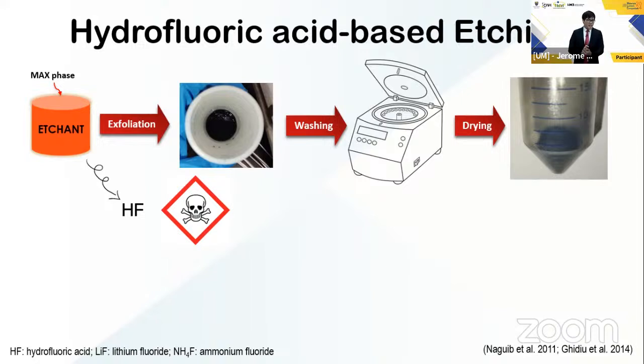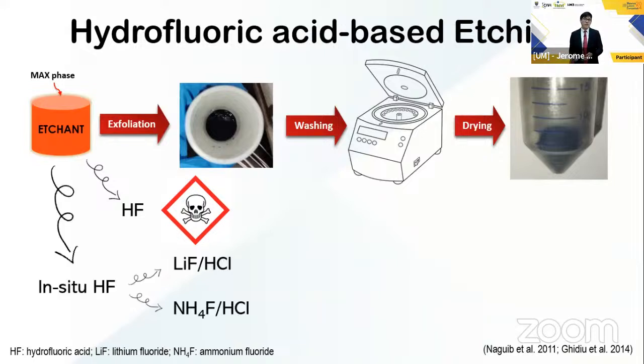But hydrofluoric acid, as all of you know, is one of the nastiest chemicals one can ever come across in the synthesis. So naturally, researchers try to avoid using hydrofluoric acid and search for alternatives. The first ever alternative discovered was in situ HF in 2014. It is a mixture of fluoride salts and hydrochloric acid that forms hydrofluoric acid on site, in situ, as it reacts with the MAX phase.